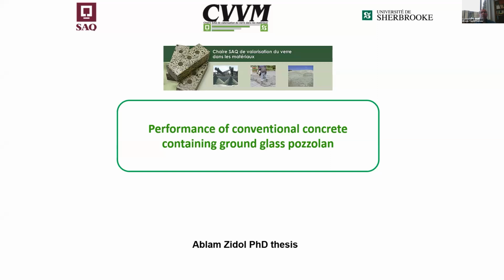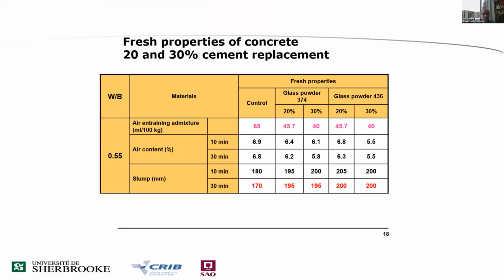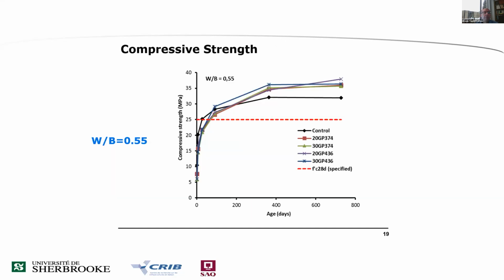The mechanical performances of this glass in a conventional concrete are presented here. So we worked with two finenesses here, and you can compare with the control. We can see here that the rheology, or the slump, is not really affected, that we can have a good slump with glass because its absorption is almost zero. But we have two finenesses here, at 20 to 30% replacement. So we can have very good compressive strength if you give time to the glass to react. Of course, like other SCMs, it is slow in reaction.